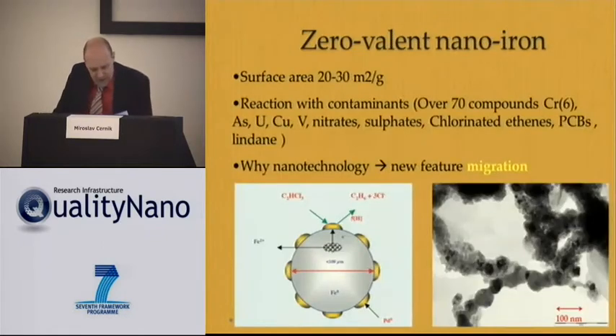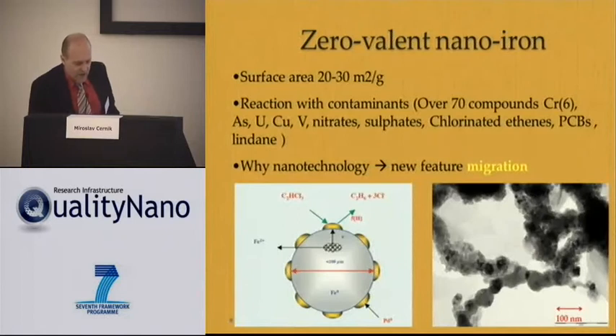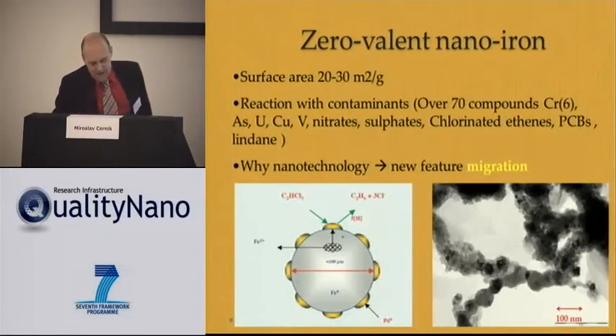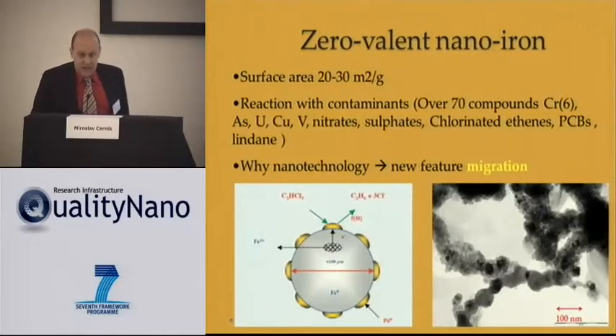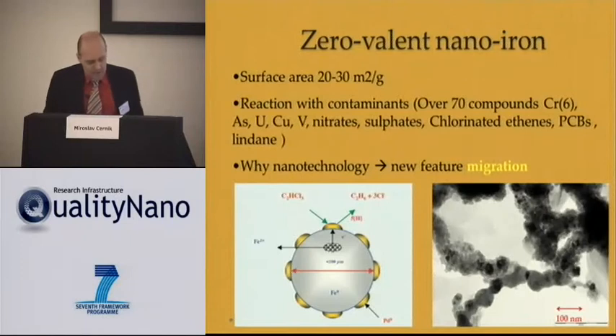One of the possibilities is to use the iron nanoparticles, which have a size of about 80 nanometers. They have a surface area exceeding 20 square meters per gram, and you can find in the literature that they work with many potential contaminants like chromium-6, arsenic, uranium, nitrate, sulfates, chlorinated ethenes, which are the most spread pollutants, PCBs, lindane, for example.